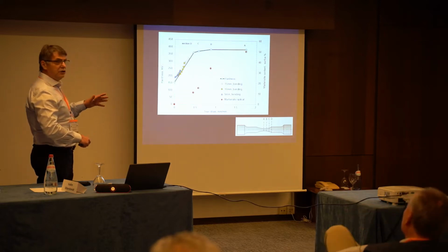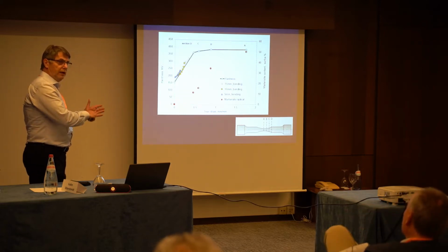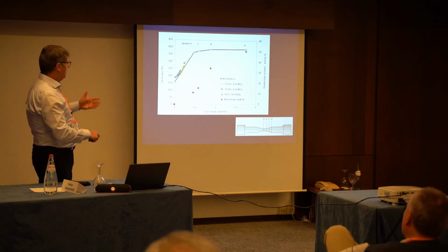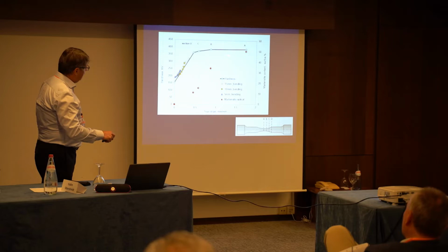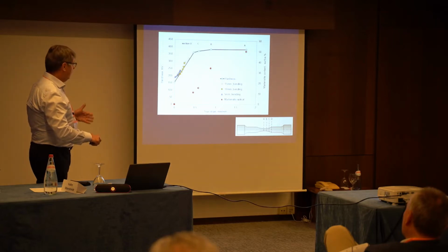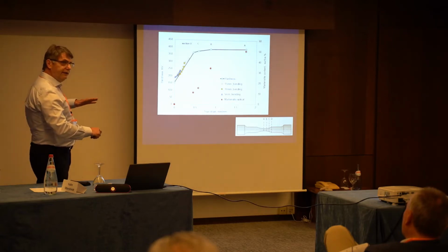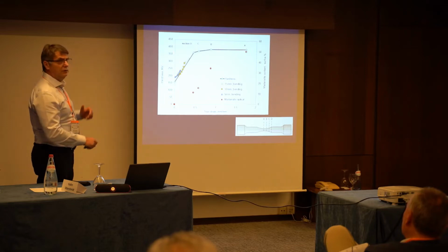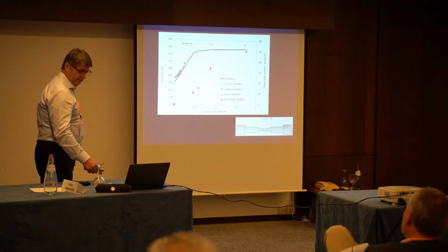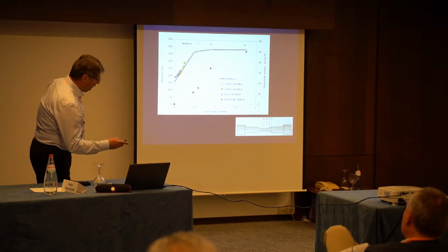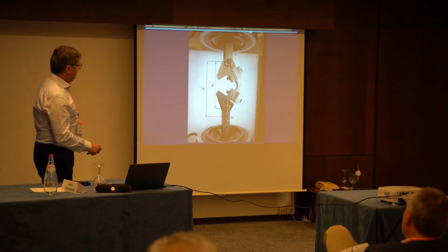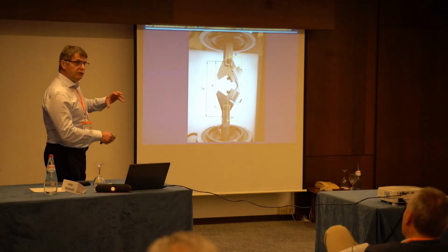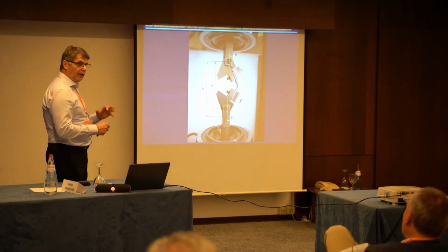There is some correlation between these values which you measure from the surface and also with the martensite content. And hardness does not increase linearly after 50%. Actually, you get a plateau of this value. So if we go now to the next slide, these are the geometry parameters which we should consider in our analysis.